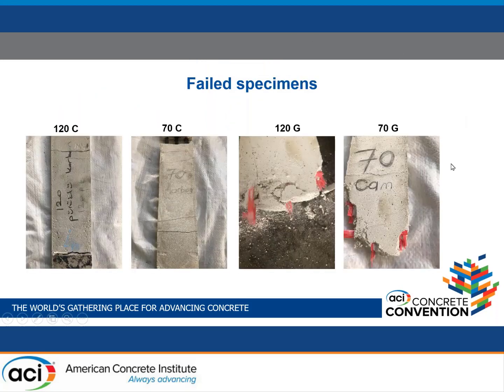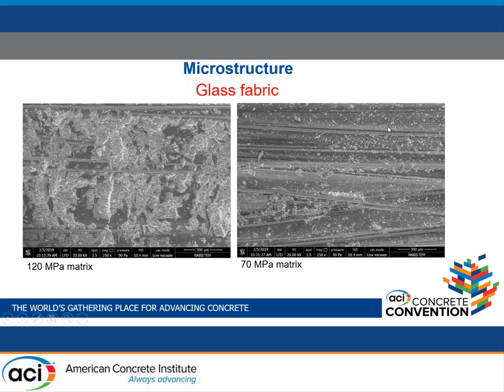So in this slide, you see the samples after failure. It's just a photograph, but you see the very fine cracks in all the samples. These fine cracks help to improve the energy absorption during the test, during loading.